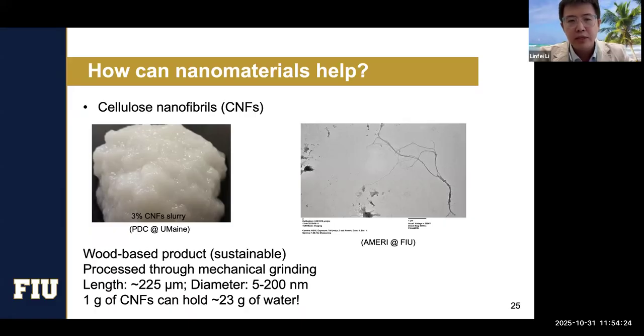We know this material has a length around 225 micrometers, but the diameter is in the range of 5 to 200 nanometers. So that's why we can call it a nanomaterial. And the other thing, just to give you data, based on what we found so far, 1 gram of cellulose nanofibril can hold more than 23 grams of water. So that's impressive. This is why we started thinking we can use that for internal curing purposes maybe.